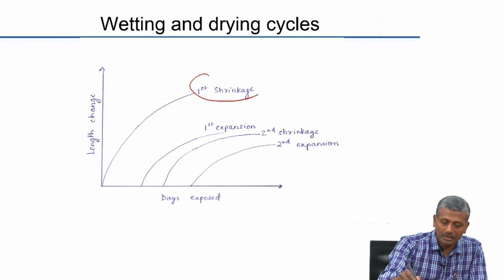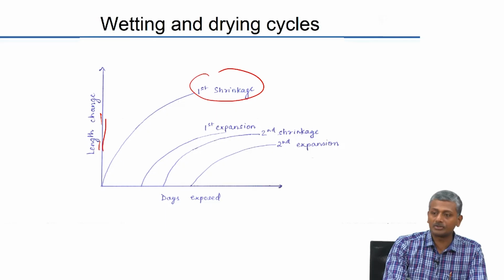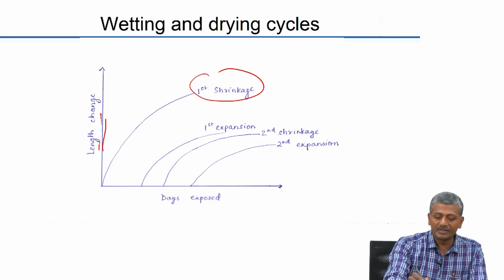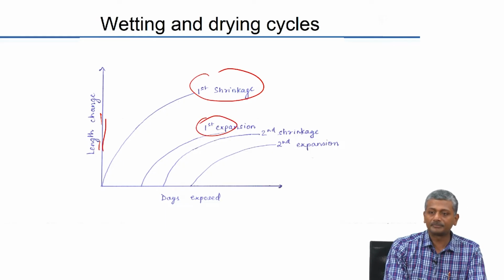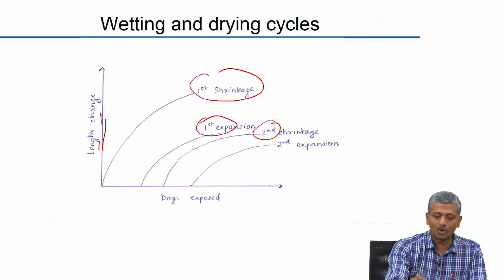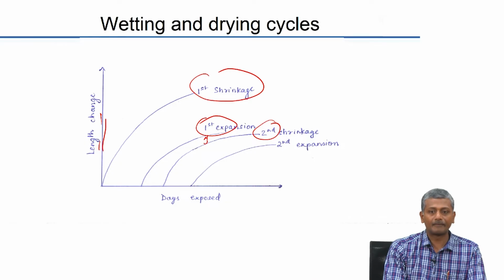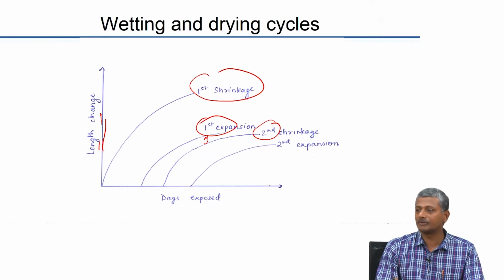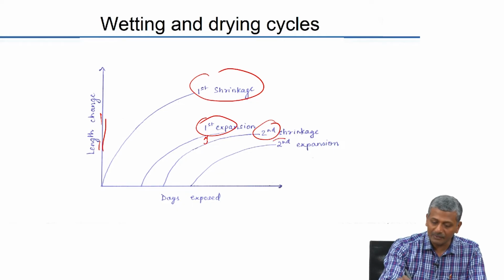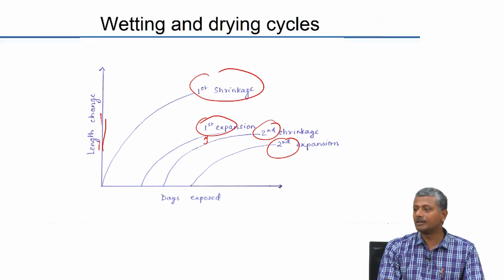The first shrinkage produces the maximum change in length or change in volume of the system. The first expansion is a little bit smaller. The next time that it dries out, the level of shrinkage is again smaller than the expansion, because then only part of this water can get pulled out at the same levels of drying conditions, and subsequent expansion on rewetting is again lower than the shrinkage that actually happens.